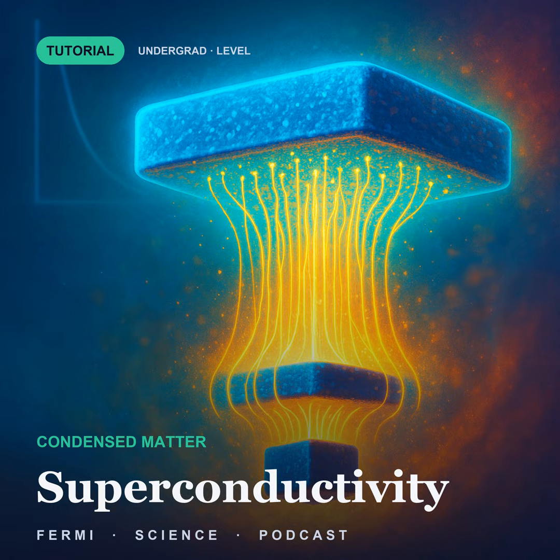But now the charge earns its keep, because a charged order parameter gives you a second length that helium had no way of producing. A varying phase in a charged system is an electric current. A current makes a magnetic field, and a magnetic field pushes back on the current that made it. Follow that round the loop and tell me what happens to a field trying to get into the material. It gets screened. The field enters at the surface, sets up currents, and those currents produce a field opposing it, so it dies as you go in.